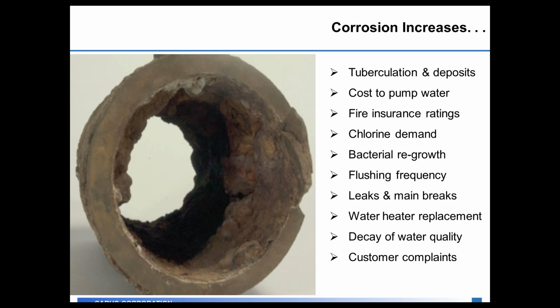Have you had any issues with bacterial regrowth or hits with bacteria out in the distribution system? Bacteria can be a major form of causing corrosion out there in the distribution system. Do you have a lot of issues with dirty water, red water complaints in the distribution system, and you're sending your team out to flush the fire hydrants frequently? And when they do that flushing, do they have to flush the fire hydrants for 5 minutes, 10 minutes, 30 minutes? The longer that you have to flush the fire hydrant until you get clean water is a good hallmark that you have a lot of corrosion going on out in your distribution system.